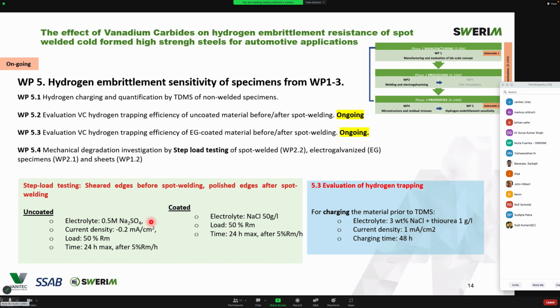Concerning hydrogen trapping, we use thiourea, which is also based on some sort of organic thiocyanate. But these results are not in context with the good results we obtained in this work, that 0.3 vanadium addition shows better mechanical performance. So this is just to accelerate the hydrogen uptake and to see some effect on the carbides, how they perform in the hydrogen trapping capacity.